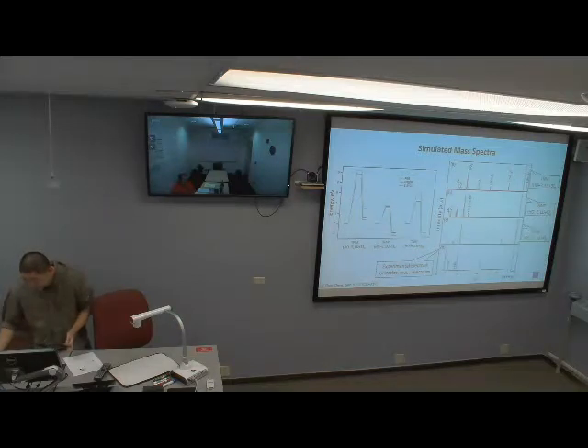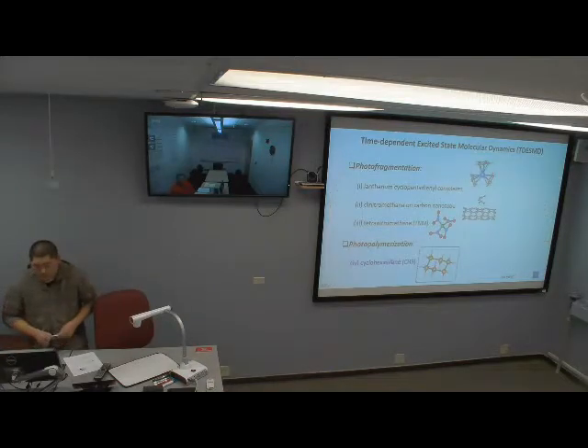For the experimental mass spectrum, we do not observe this molecular ion peak. This is because high energy electron impact creates high energy molecular ion, which can very quickly dissociate. Okay, so the final application would be photopolymerization of cyclohexadiene by TDESMD calculations.